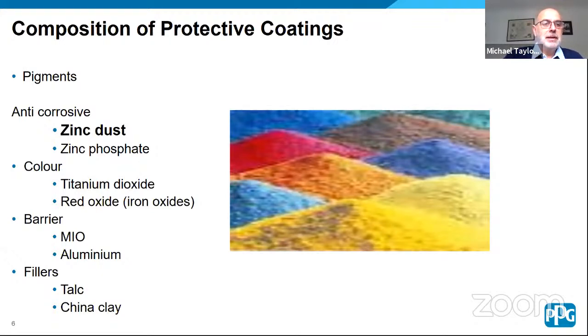a bit more expensive. Other types of pigments we use are barrier pigments, so aluminium flake or MIO, micaceous iron oxide. These pigments are flatter in their shape and act more as a barrier to decrease water permeability through the coating. And the final type of pigments are what we call fillers. So these are usually dug from the ground: china clay, talc, barytes, barium sulfate. They tend to just give us extra volume solids into the coating, but they're fairly inert. They don't have any particular other reason to be in the coating other than that.